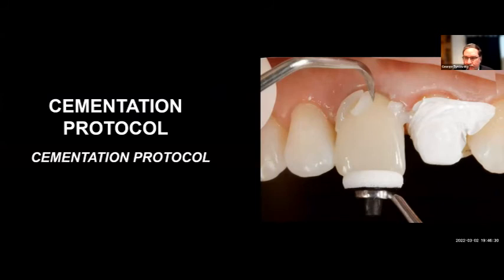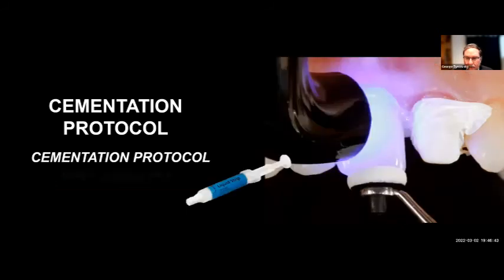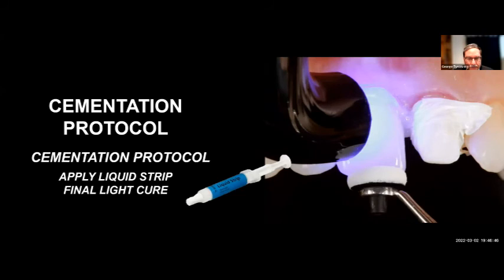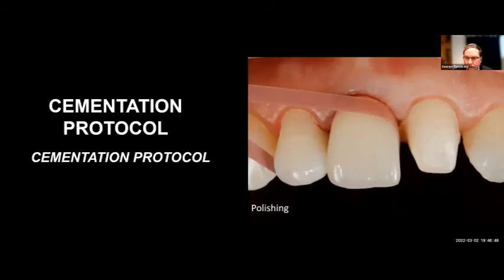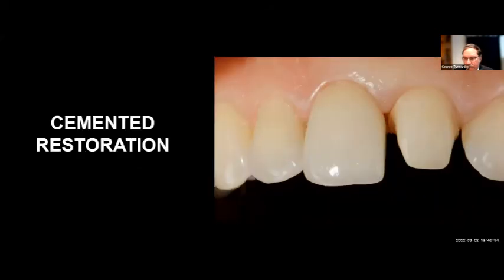So here we are cleaning it up, peeling it off, and basically by doing this wave technique, it's in a rubberized gel format, so it's easy to peel off before final full polymerization. And then we can go through final polymerization, final curing, holding the restoration in place, polishing, cementation, of course. And then we have a final cemented restoration. So again, that's total adhesive technology, which is used for glass ceramics, especially for anterior restorations, partial coverage, inlays and onlays, and for full crowns as well, depending on the clinical case.